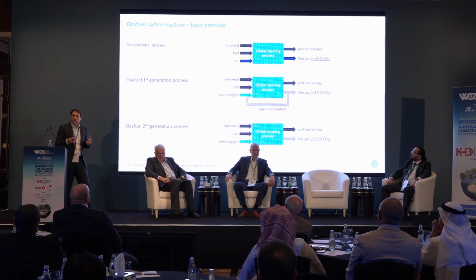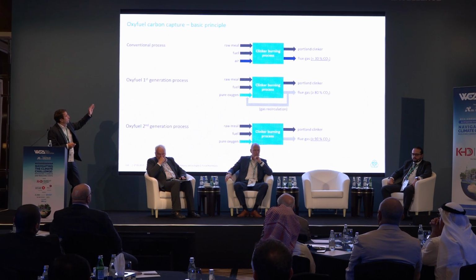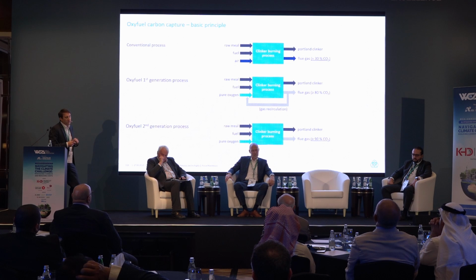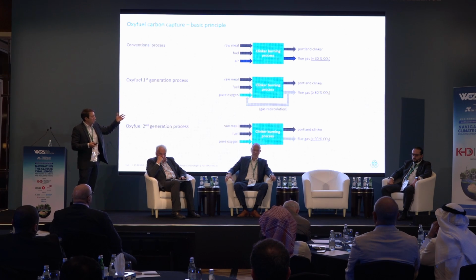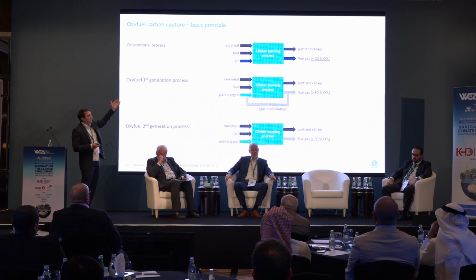In parallel, we have been working on oxyfuel carbon capture. Just very quickly, because I'm not the specialist here and time is limited: in a conventional process, you input raw meal, fuel, and air into the system, and you have an output, of course, the clinker, and 30% of the flue gas is made out of CO2. In the oxyfuel second generation process, the idea is to inject pure oxygen into the system, and what you get in an airtight system is around 90% CO2 in the flue gas. Then the carbon capture is much more efficient, capturing out of 90% rather than 30%.